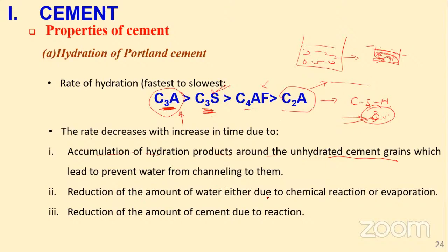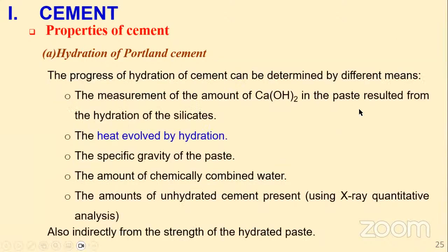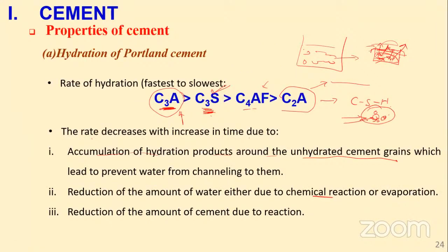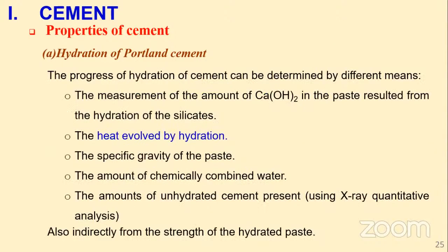So this water continues reacting in here and it diminishes. So the reduction in the amount of water, either through chemical reaction or some water evaporates. And this is not desirable, but that's why we do curing. We cover or we continue pouring water to replace what was lost during evaporation. Or the reduction, of course, these unhydrated grains continue decreasing, okay? They continue reacting. So as this reaction occurs, you have seen for all the four reactions, heat is generated. So the chemical reaction of cement when it's coming into contact with water is exothermic. We need to understand about the heat of hydration that is involved, okay?